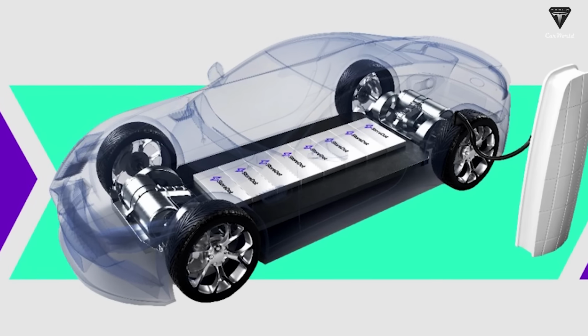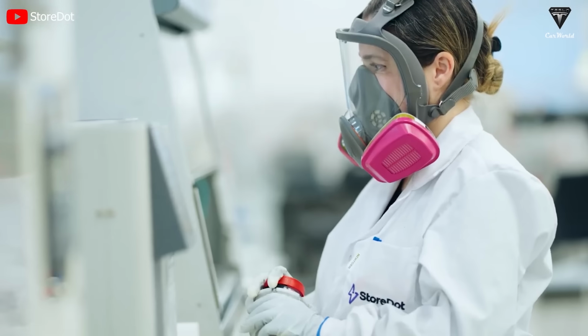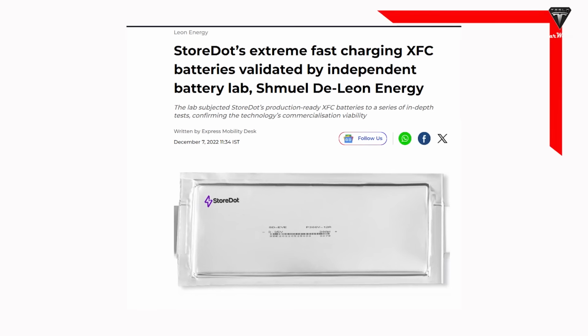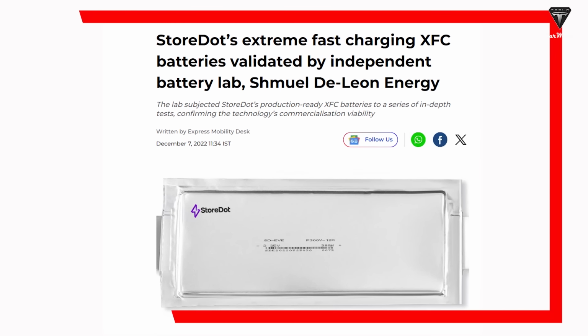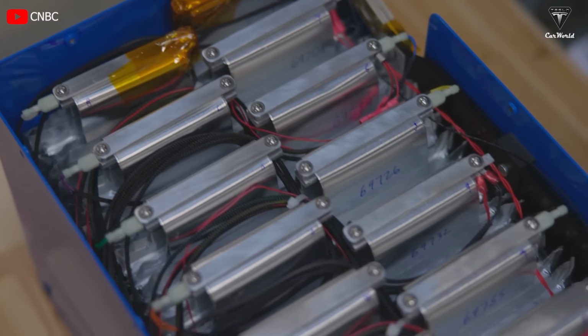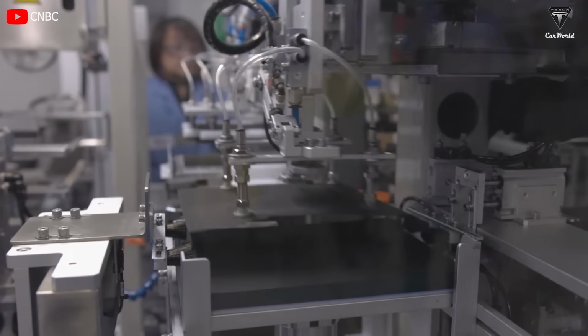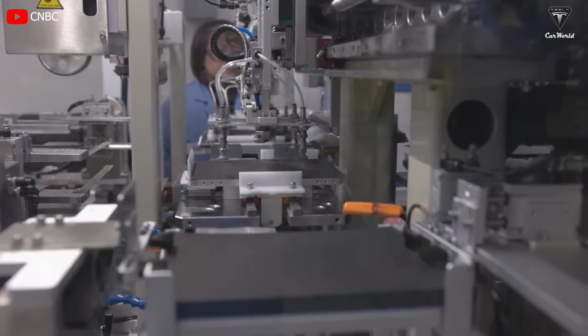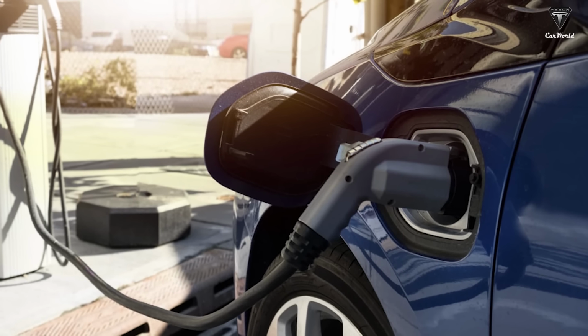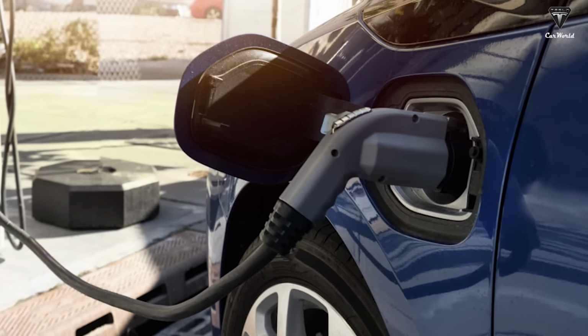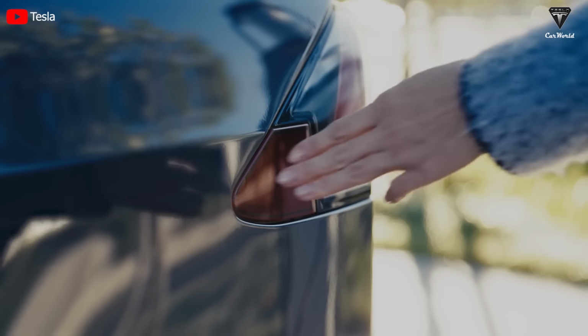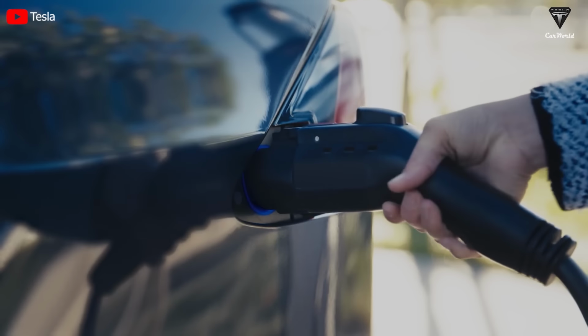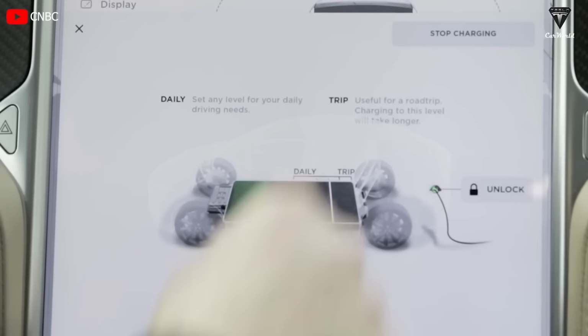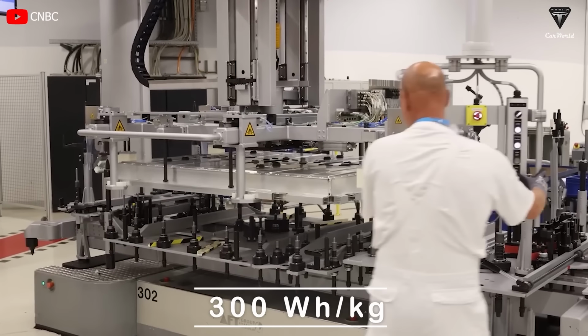Interestingly, a third-party assessment of StoreDot's XFC battery technology has yielded very positive evaluations for this type of battery. Shmuel De-Leon Energy, or SDLE, an independent battery laboratory, tested StoreDot's XFC battery at the end of 2022 and concluded that this type of battery is ready for electric vehicle production. They highlighted the technology's superior fast charging capability, high energy density, and commercial viability. SDLE conducted tests on this EV battery through 1,000 consecutive fast charging cycles to complete evaluations related to energy density, charging speed, operating conditions, and cycles. The test demonstrated that the battery leads in energy density, reaching 300 watt-hours per kilogram.